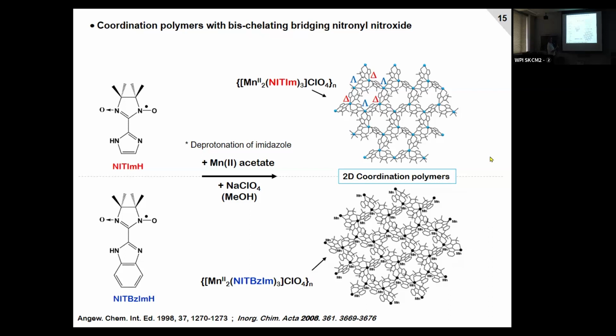So you have manganese, radical, manganese, radical. This is the 2-dimensional network. And if we look at the conformation of the ligands, when you have 3 radical ligands like this around the metal center, you have 2 types of topology. One is delta topology and another is lambda. In 2D systems like this, you always have the 2 topologies: delta, lambda, delta, lambda. You have an alternance of conformation around the metal center.